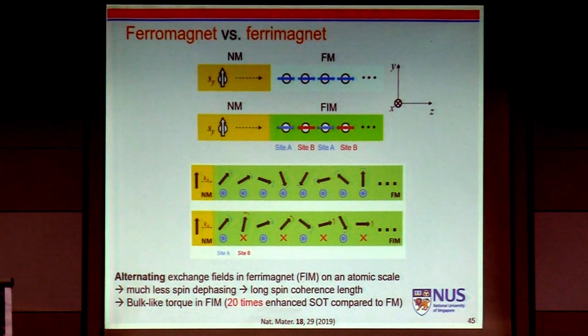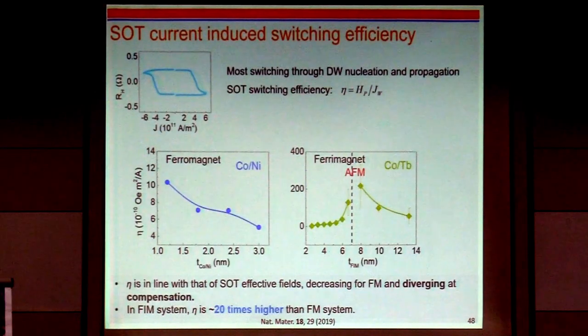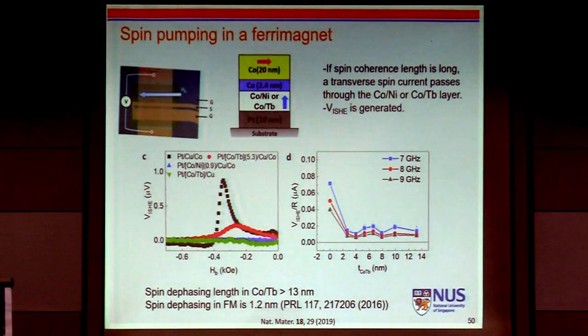So anyhow, we show the spin torque efficiency improves about 20 times once we have the superlattice. So if you remember the previous alloy, we showed the 10 times enhancement, but by doing a multilayer, we improved another 2 times more. So I'll just skip all the details. Then I just want to show this data.